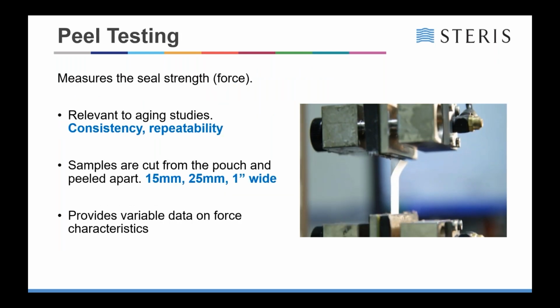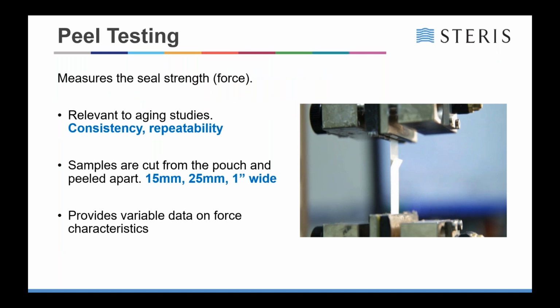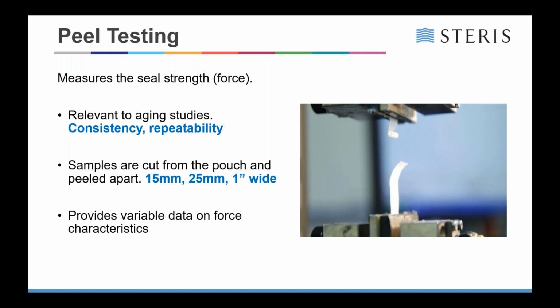In relation to peel testing, you can see the video that's running here at the moment. All it's doing is you cut a sample out of the pouch and you put it into the jaws of a tensile tester and press start. And that will give you the details on the actual seal itself, which we'll look at shortly. Again, what you're looking for is consistency and repeatability.